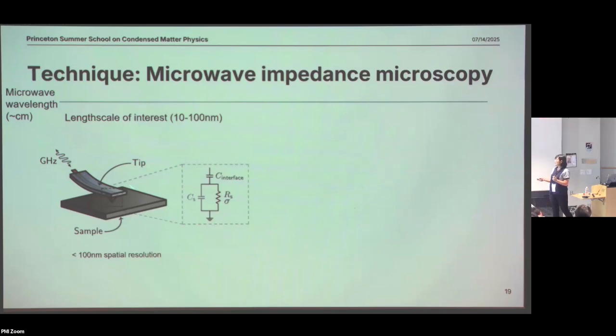One way of doing that is through confinement on a metallic tip. The tip acts like a small antenna. It's long, but narrow, or small in diameter. Its diameter can be on the scale of 50 nanometers or 20 nanometers. Then you send in a gigahertz wave, not directly from leads on the sample, but through the tip. When you're sending microwave through the tip, the sample has a coupling, and that coupling can be written in this circuit model here. You have a capacitance at the interface of tip and sample, and then the sample has a resistor and a capacitor. So it can be modeled this way.